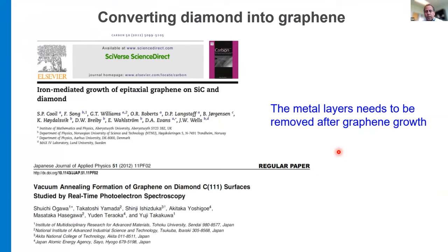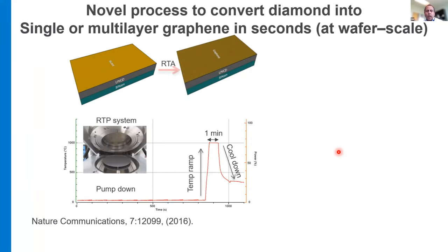But in the first case, you have this metal layer that needs to be removed after the growth. And in the second case, the graphene that you grow is in a vertical direction, not in a planar one. So we wanted to see how we can do this on ultra nano crystalline diamond, which is a polycrystalline diamond. So we came up with a process where we grow a very thin layer of nickel, which acts as a catalyst, onto the diamond surface, and then do the rapid thermal annealing just for about a minute.